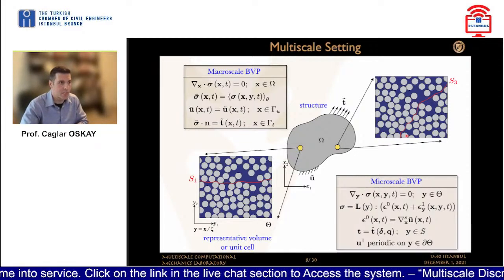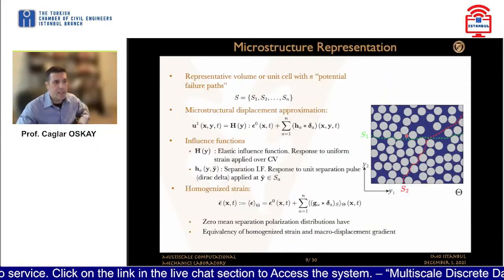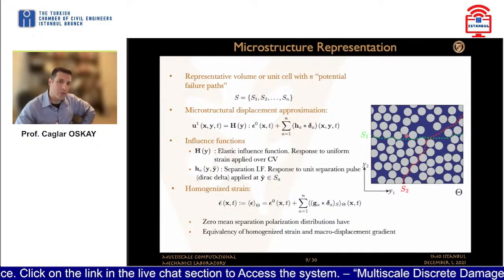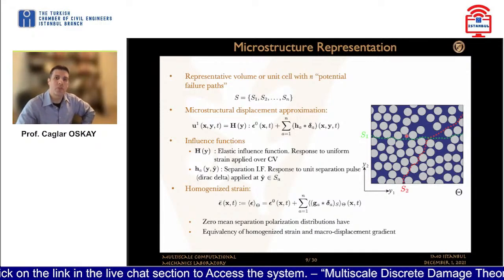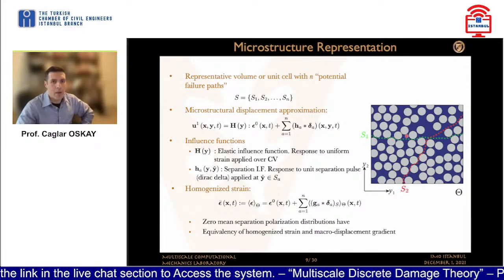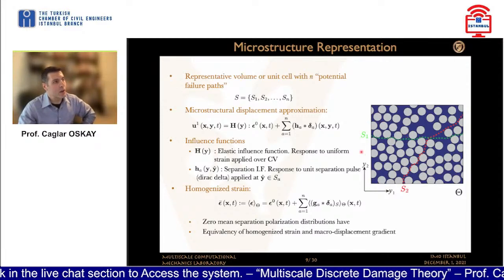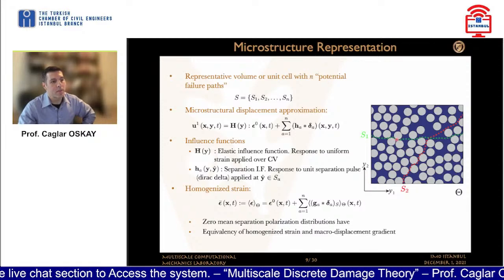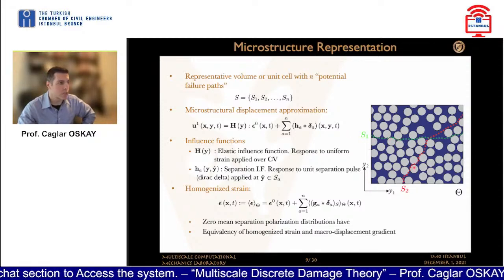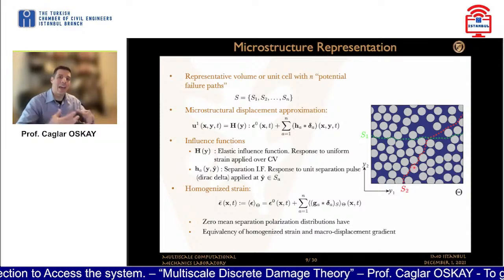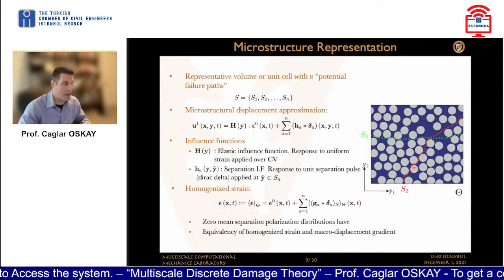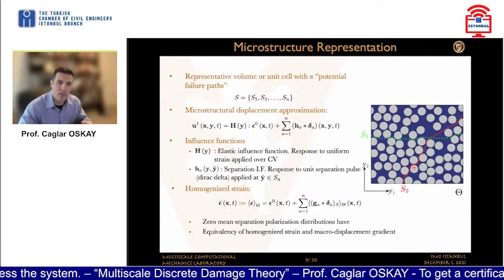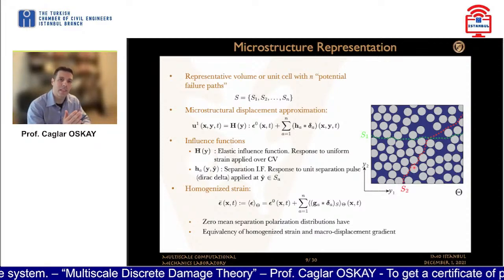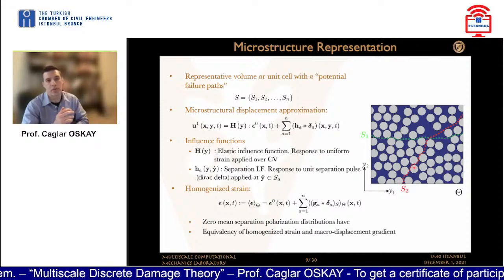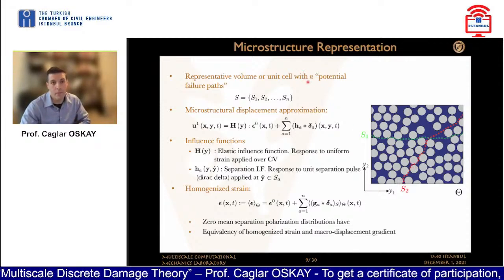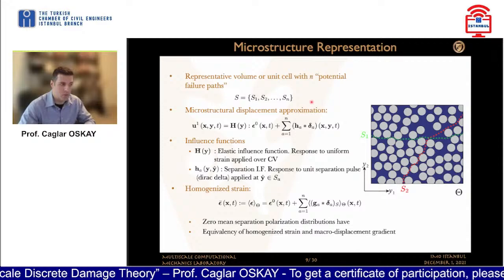when we're building our system. So what we do then is consider the microstructure, not just the geometry of the microstructure, but the geometry plus a series of what we call potential failure paths, like S1 and S2 and so forth, as the representation of the microstructure. So it is not just the microstructure geometry anymore, but these series, a discrete set of potential failure paths. And there are n of them available in our microstructure.